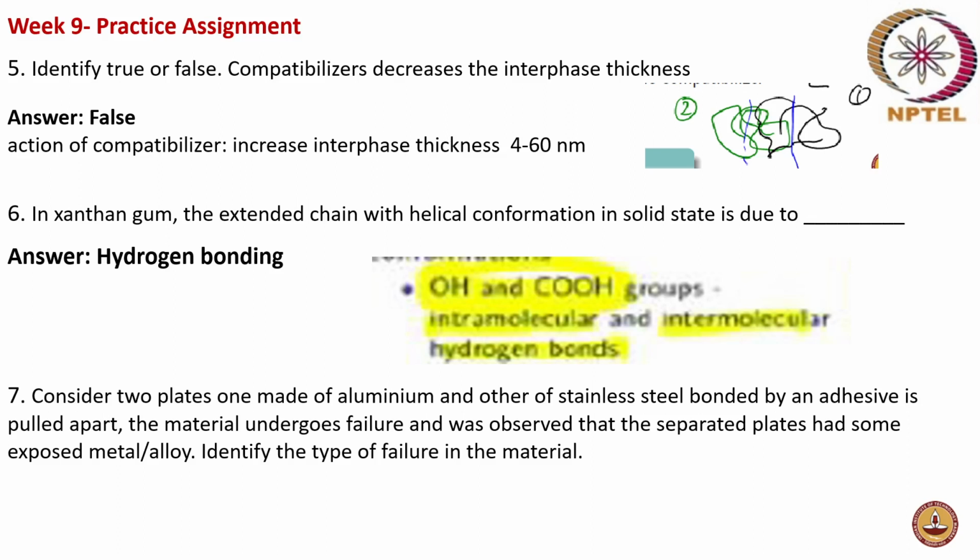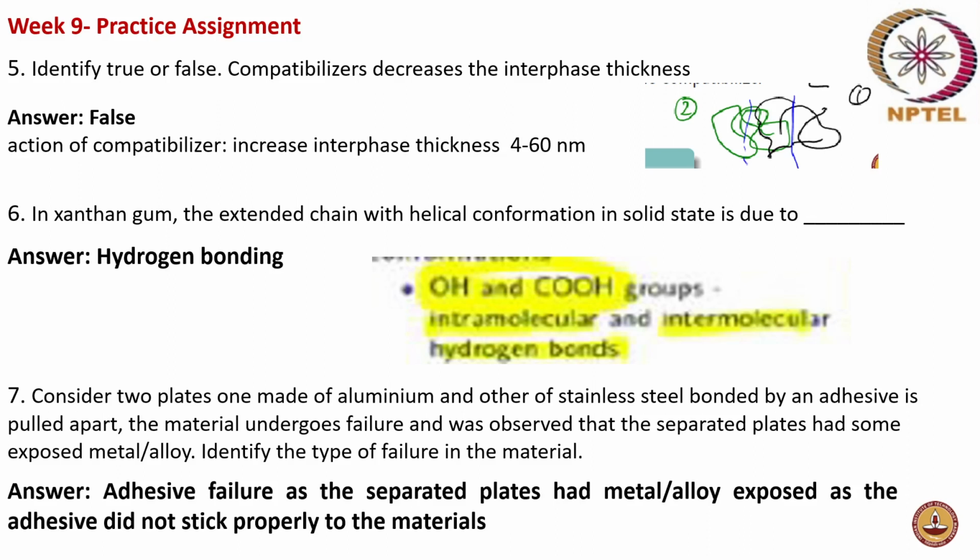I'll say one more thing. You're right. Your answer is right. Because the metal plates are exposed, at the same time the interaction between the adhesive and the metal plates is also not good. Yes, you're right. So adhesive failure is the case in this one.